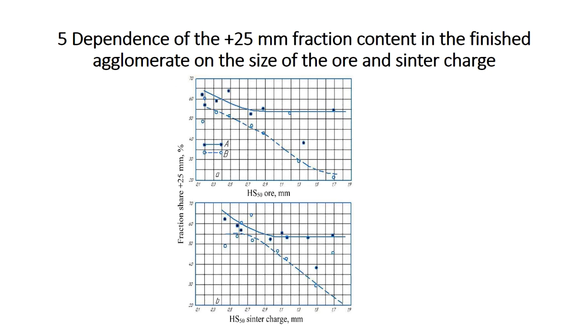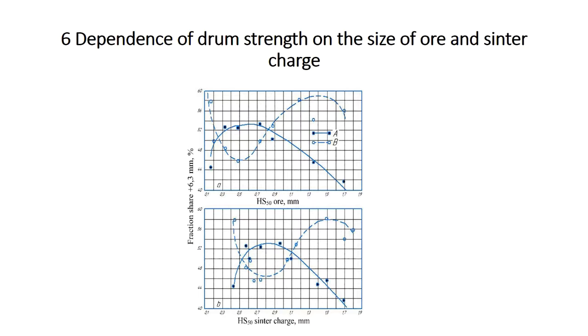Tests have shown that the abrasion of the agglomerate from hematite ore is 7.6 to 5.3 Wt%, and there is a tendency to decrease it with an increase in the size of the ore. For agglomerate from magnetite ore, abrasion is 8.0 to 6.4 Wt%, and in this case there is also a tendency to decrease it with an increase in the size of the ore. The maximum abrasion was observed at an Hs50 value for a charge of 0.6 to 0.7.